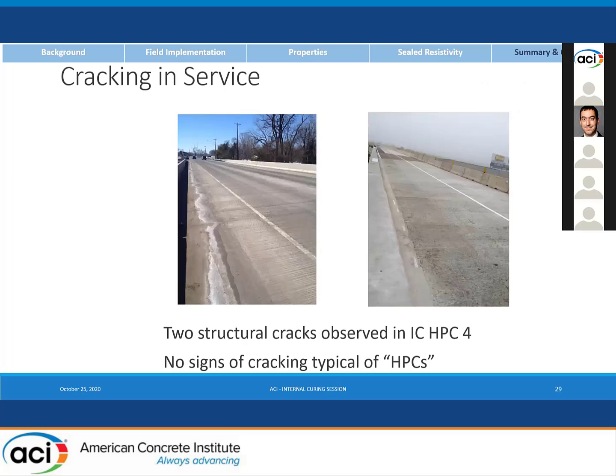And so rounding the bend here, I will just wrap it up with what we've actually seen so far. The primary cracks that I saw when I observed these within the first year of construction: there's two structural cracks at an integral pier on one of the bridge decks, and so that's primarily just a design consideration. No sign of any typical regularly spaced transverse high performance concrete cracks.